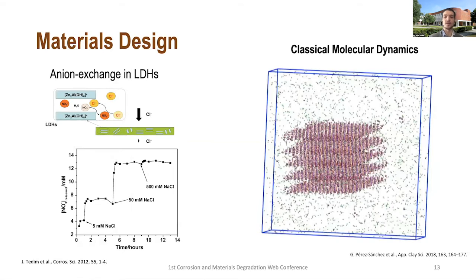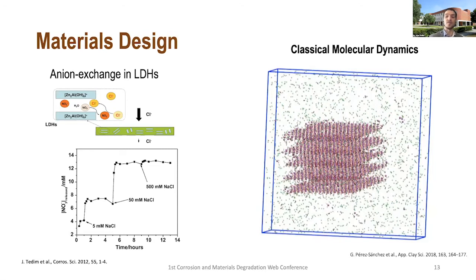Perhaps one of the most interesting things that we have associated with LDH is this controlled release, this ion exchangeability, on having exchange of intercalated inhibitor with some species in the environment, most notably chlorides. We have seen in 2012, in one of the studies where we have published, that there was a controlled dependence on the nitrate release from the LDH in the presence of chlorides. More recently, we tried also to use molecular dynamics to try to see the very first beginning of this interaction.